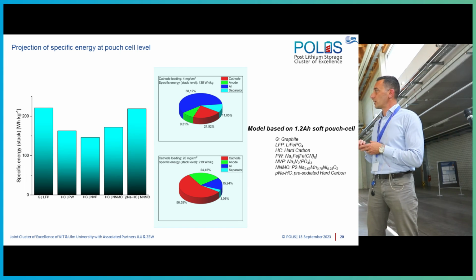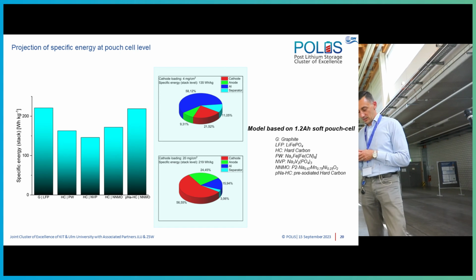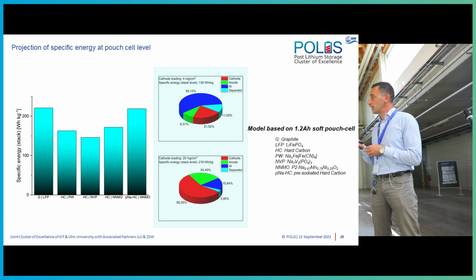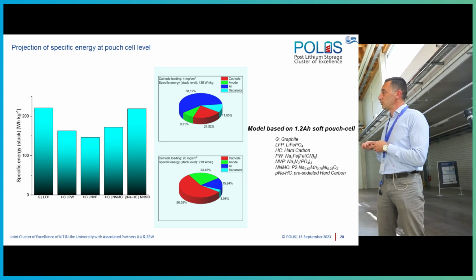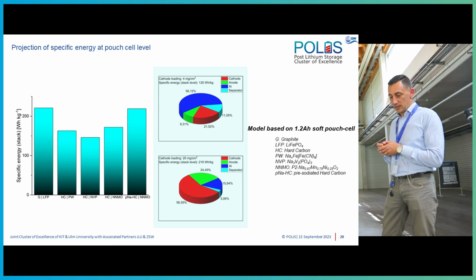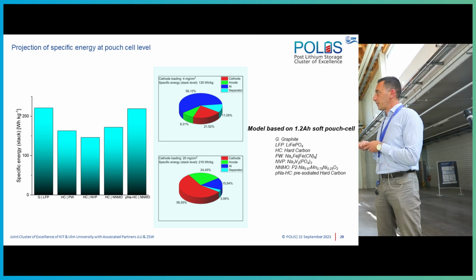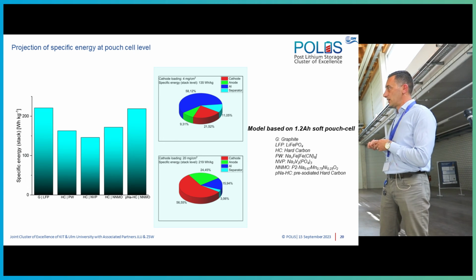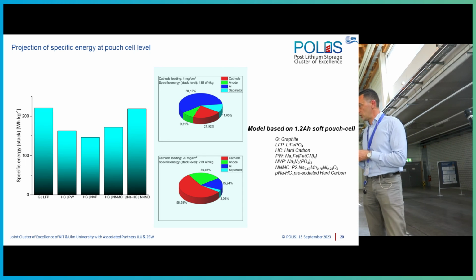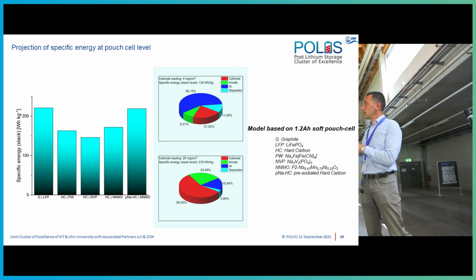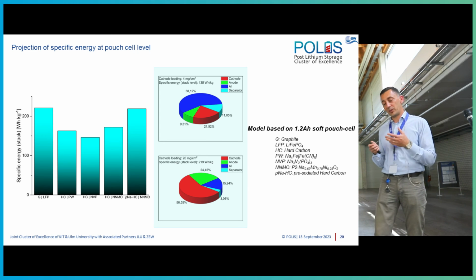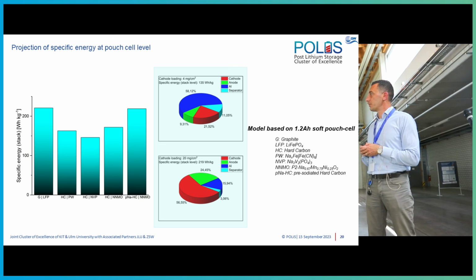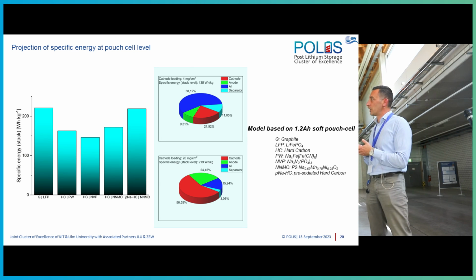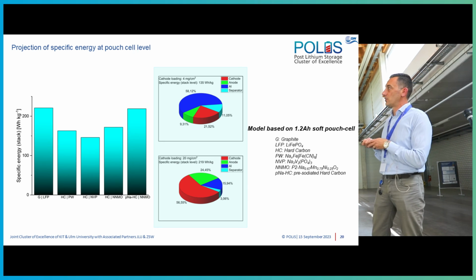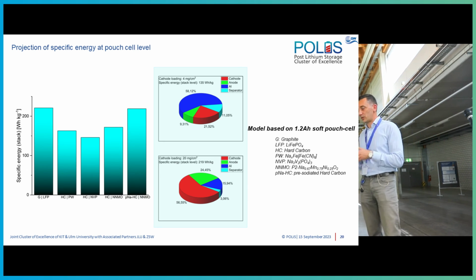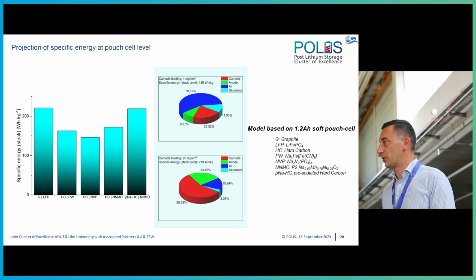As a reference, I think this is pretty standard, we take the graphite LFP cell. And then I compared that with the different cell chemistries. Of course, I always kept hard carbon at the anode side: Prussian white, NVP, and then our material, in this case, baseline. What we see is that if we do not pre-lithiate or pre-sodiate the hard carbon, the specific energy will be low. Please note that this is at the stack level, so electrolyte and pouch pack are not included in the weight of the cell.